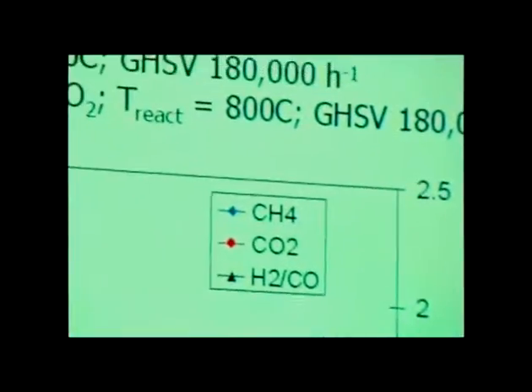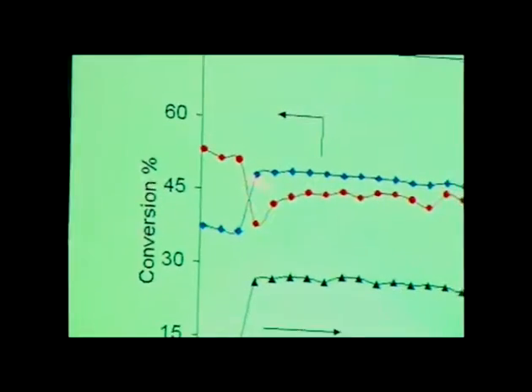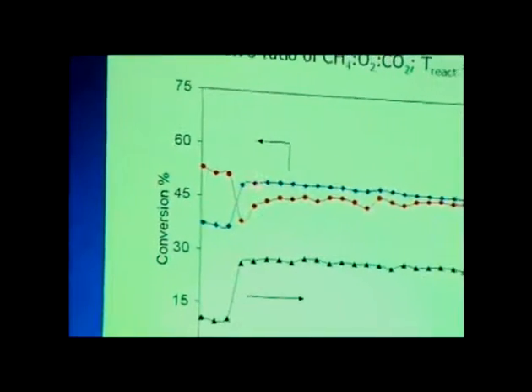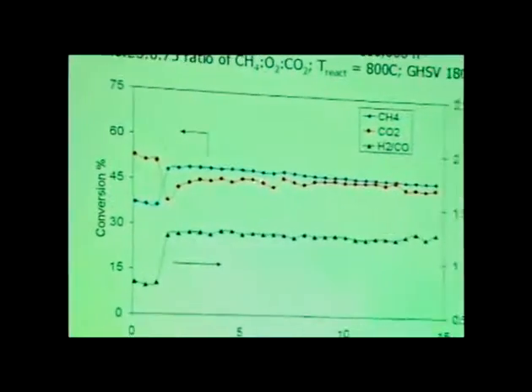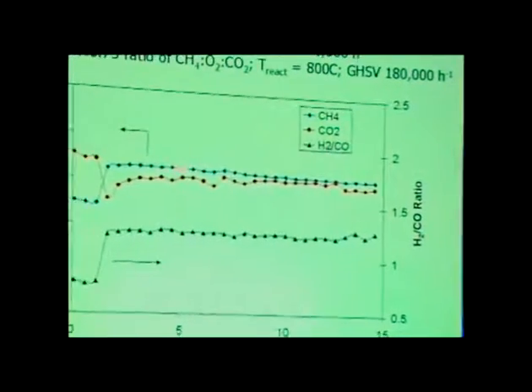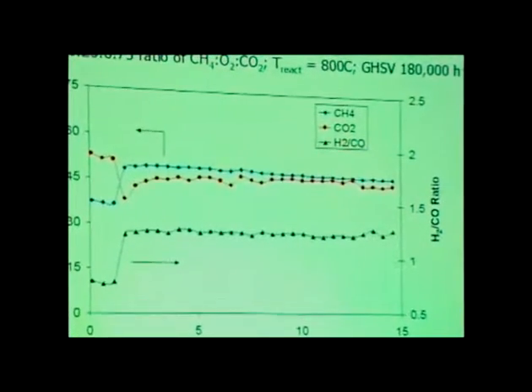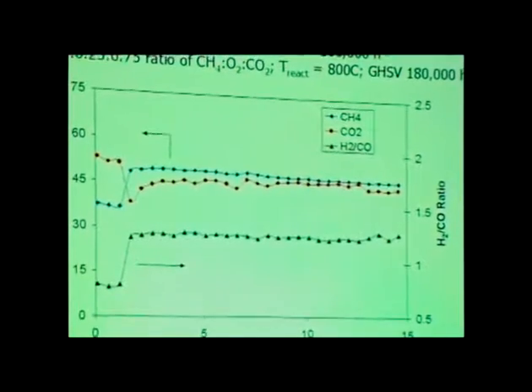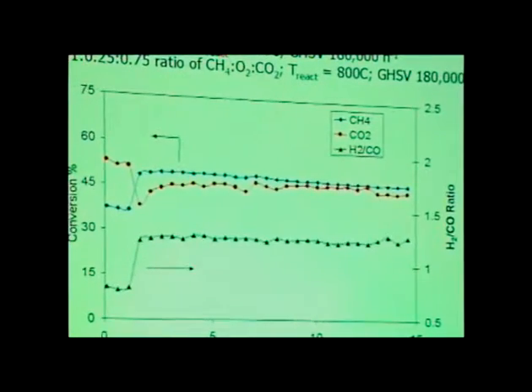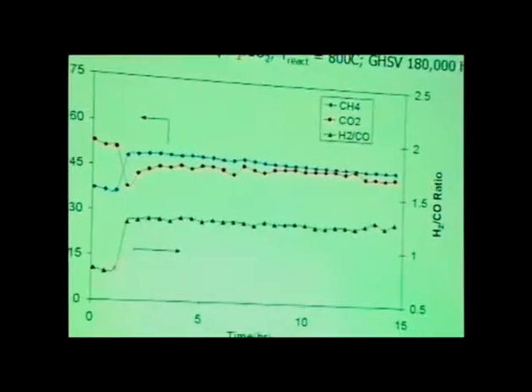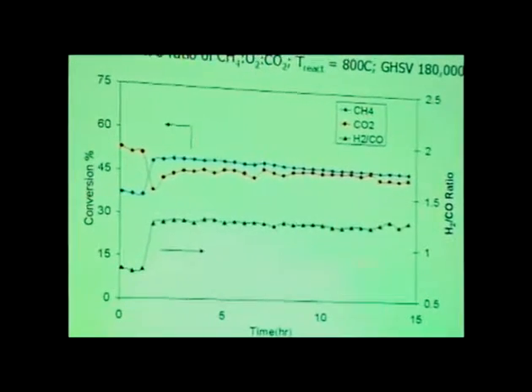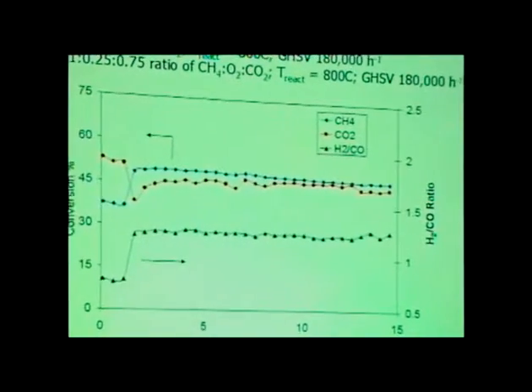Just to show, at the last slide, is to show the ability to tune the hydrogen to CO ratio on the platinum ceria-zirconia. We can run the dry reforming reaction for about an hour and a half. We can switch now and add oxygen at a ratio of methane to O2 of 4 to 1. And we see that we really have no significant change in our activity, maybe 1% or 2% different from when we ran just purely in the presence of CO2. And our hydrogen to CO ratio, again, we can change it from roughly 0.7 or 0.8 up to 1.4.